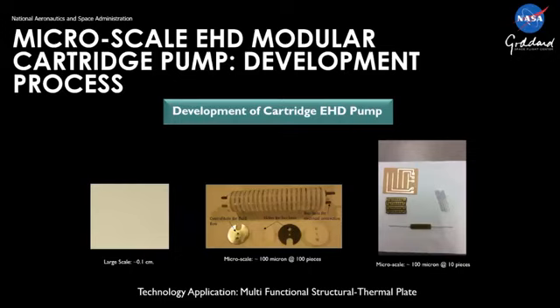So a little bit of the history. I think the picture on the left is not what I was hoping for. That's a larger scale EHD pump that's probably 20 years old. Basically, it is a number of tubes inside a larger tube that's about 1/10 of a centimeter in diameter. We move down to the micro scale, basically hundreds of microns of characteristic dimension. That is the dimension between the two stages, the positive and negative electrodes. But this is about 100 pieces you see in the middle here. You see the 4 component pieces, and then when you add in the Teflon and the spacers and the various electrical bus pieces, you're up to about 100 pieces. The big advance that we made is we dropped this down to about 10 pieces. And you see that on the right-hand side. And these are the actual pumps that flew on STP-H5. Next slide, please, Sean.